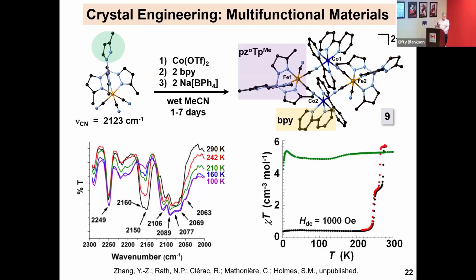The magnetic properties are pretty interesting. If we remove the solvent, you can see that it's relatively flat. It's trapped in this paramagnetic state, meaning that presumably the lattice has collapsed and you can't elongate or expand the cluster. And so the energy barrier is too high for it to do it, so it doesn't. But when you have the solvent molecules present, you get a two-step transition, suggesting that you have two energy costs for electron transfer in the same molecule.